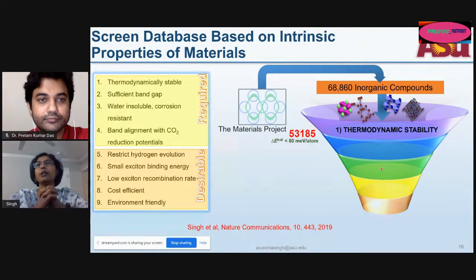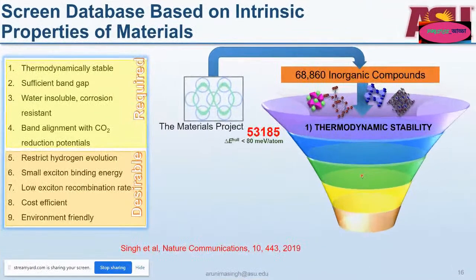And since the Materials Project has this computed already, what we needed to do was identify a cutoff for that energy, which is a measure of the thermodynamic stability, and pass the 70,000 candidates through this first screen of ours. We selected a criterion of 80 millielectron volts because that corresponds to synthesis temperatures of about 1,000 Kelvin.